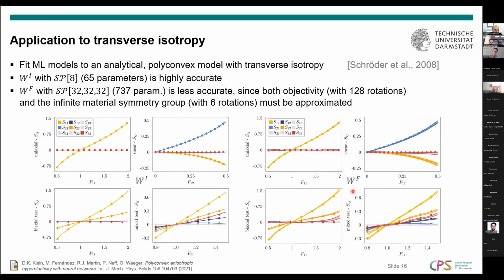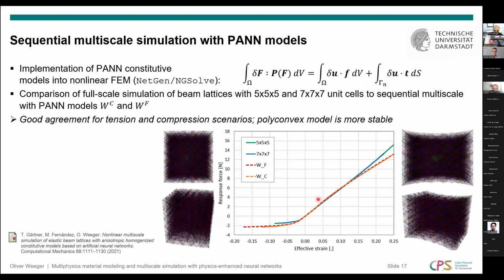For the WF model, the prediction is not as good, and we need a much bigger network now, because for transverse isotropy, we know which invariants we have to use, but the symmetry group for the material anisotropy is an infinite group. So basically here we need to approximate the symmetrization operation, for which we use only 6 rotations over here, and also the objectivity, for which we use 128 rotations over here, in order to get a more or less good fit. So we need to do a lot of data augmentation for this model for it to work well. However, now we can use these models in multiscale simulations.